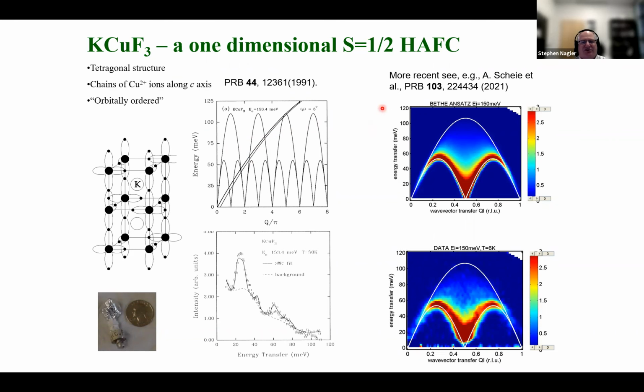So you can see we can just do a neutron scattering experiment. And here we plot momentum on the horizontal, energy on the vertical, and intensity by color. And one can do Bethe ansatz type calculations to get what the spectrum is, and you compare that to experiments, and it's very close, right? So we see these things.